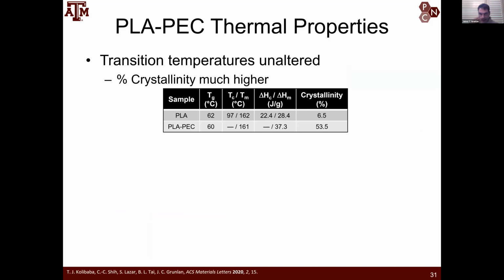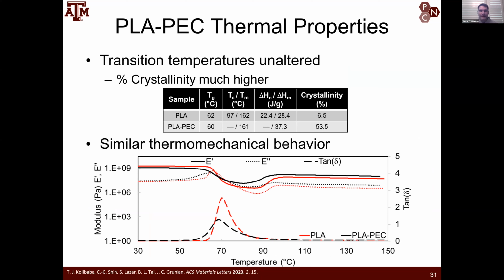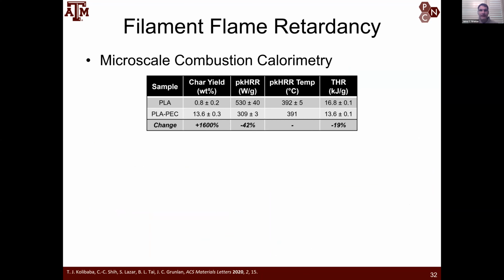And so you actually get higher crystallinity. We actually think, once again, much like with the wood, you get a stronger part created because of the polyelectrolyte complex being present. Now, when we look at microcombustion calorimetry, known as MCC, it's like a small cone calorimeter. You can see the char yield. The PLA has no char yield, and you get 13% with the combination filament. And then a dramatic reduction in peak heat release rate and a significant reduction in total heat release.